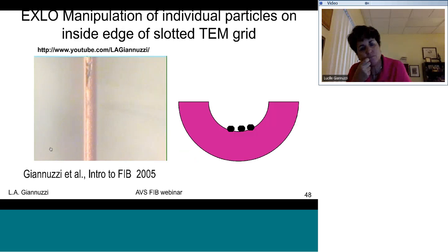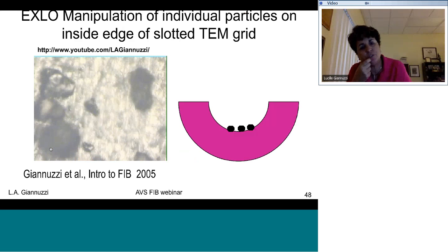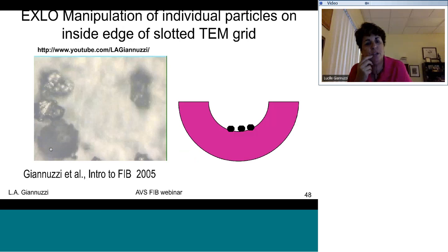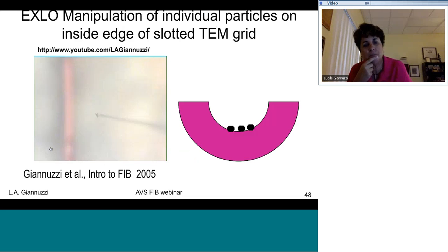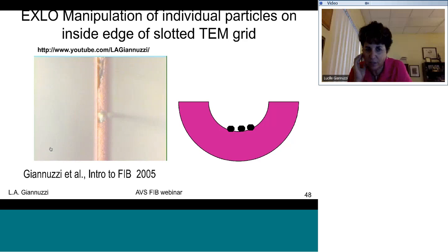And see if the glue is strong enough. If the nanoparticles are already small enough, then of course you would use a clean thread kit to mount them on there. If the nanoparticles are still too thick to be directly atom probed, then of course you can subsequently FIB mill them to the correct size. But that's what I would do. If you want to try it, you can contact me afterwards, and I'll be happy to try it for you if you don't have an ex situ station.